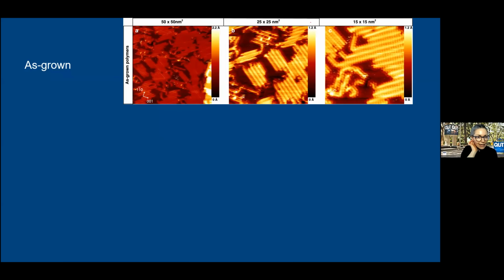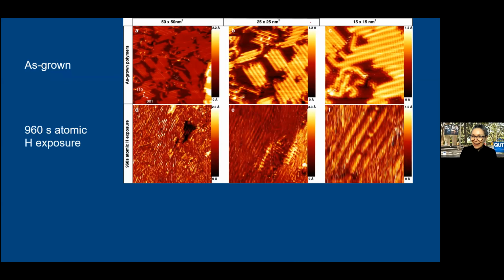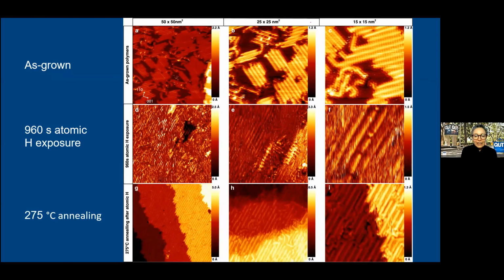In terms of what it looks like to STM, here it is. Our as-grown polymers are beautiful. You see them here at different spatial scales. In the 15 by 15, you can definitely see the halogens decorating the edges. After the hydrogen exposure, they actually look pretty terrible. So our spectroscopy looks good here. Our microscopy does not. But with a short anneal, we're actually able to restore the ordering really nicely. We see slight changes in epitaxy, and we definitely don't see the halogens retained around the edges of the polymer.